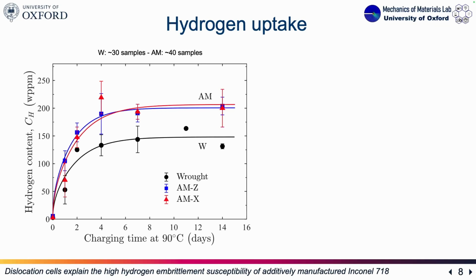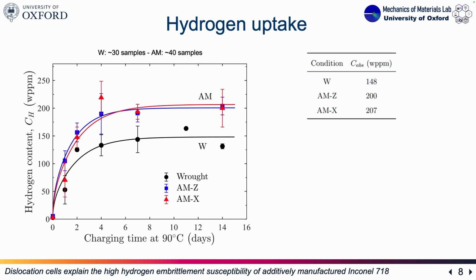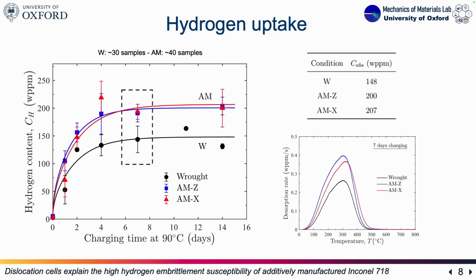This is actually the absorption behavior, where we can compare straight away the wrought versus the additive. Well, actually, I'm plotting here the total hydrogen concentration versus charging time. So the first thing that could strike us is that the additive can absorb considerably higher hydrogen compared to the wrought. And at around 7 days of charging at this temperature, we have a pretty homogeneous hydrogen concentration across the thickness of my samples. And this is how the TDS spectra look.